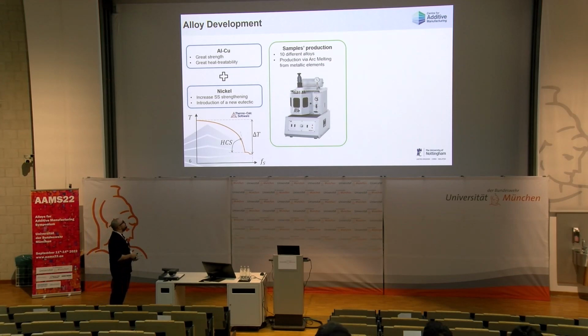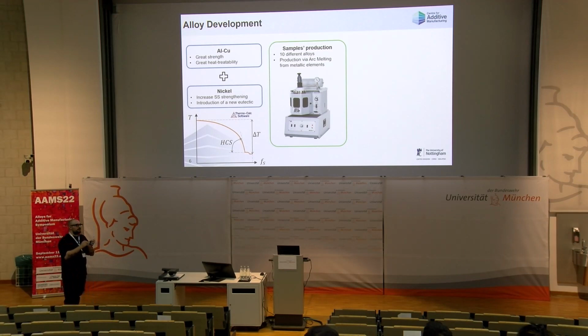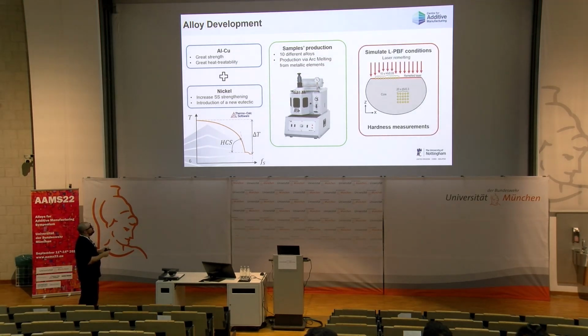Then we go into the arc melter here, and we produce different compositions. Specifically in this talk, I'm going to discuss 10 different alloys, labeled alloy 1 to alloy 10. The concept behind this is a progressive increase of alloying elements from 1 to 10. And then we need to simulate the L-PBF conditions. We do this by remelting the top layer of the arc melted button. This also gives us insight into cooling rate variability, because the button has a lower cooling rate than L-PBF, which can reach 10 to the power of 7 Kelvin per second. To validate and get an idea of the mechanical properties, we do hardness measurements, both in the bulk and on the remelted layer.